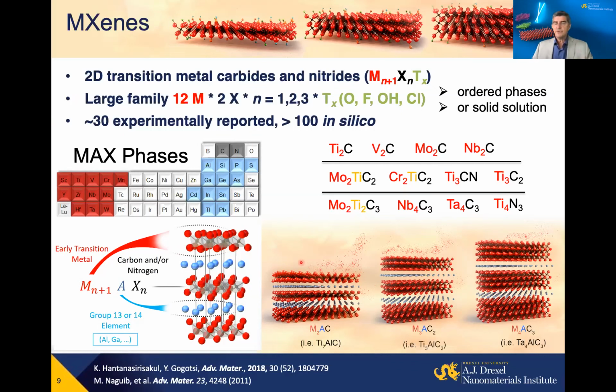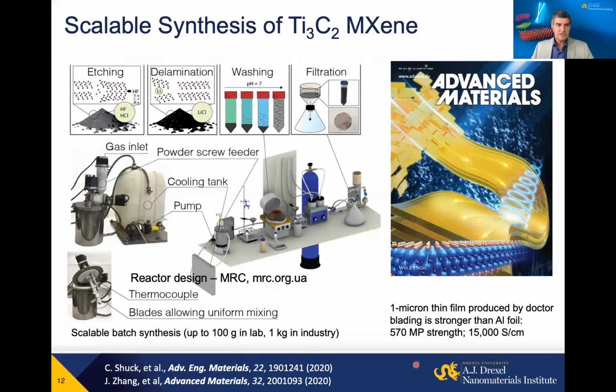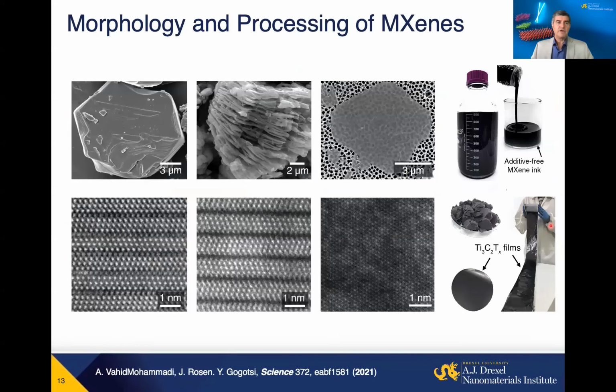We just dump the ceramic powder into solution. Stir for a while in a reactor that I showed to you, and we end up with a powder in which now there is no more aluminum or silicon or whatever was connecting these layers left. And this is now weakly bonded with OH or oxygen or fluorine on the surface particles here.